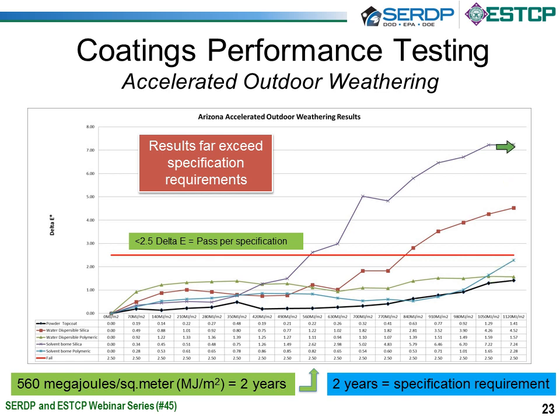Again, this data is very important because it shows all the historical CARC coatings that have been sold over the years. And I'd like to point out also we developed 3 colors during this. The tan product, another big color along with black and green, is way down in this region for color change. There's hardly any color change when doubling the specification requirements. And the green also, probably the toughest color to have exterior durability on, is still below the specification requirement after doubling the spec.